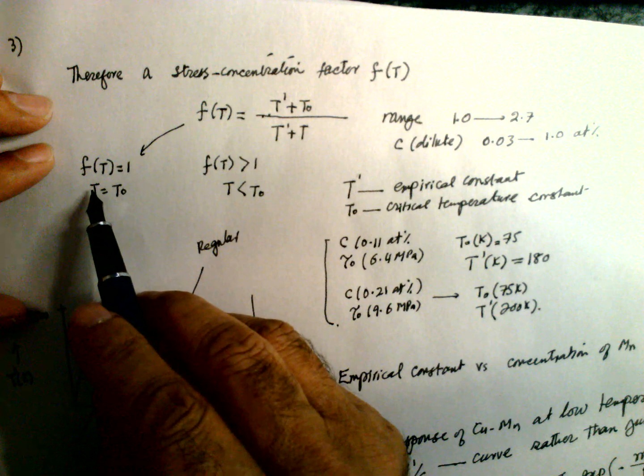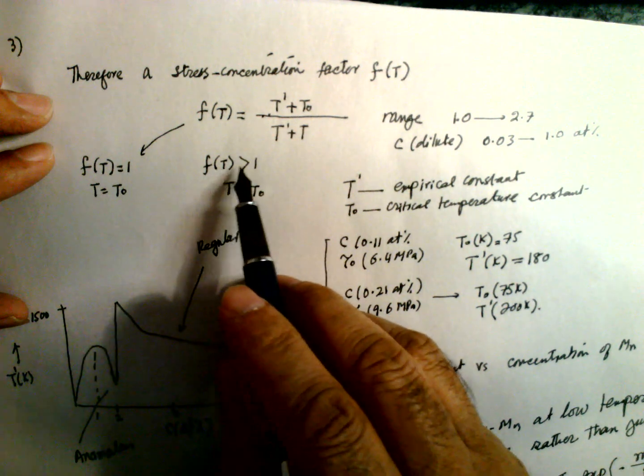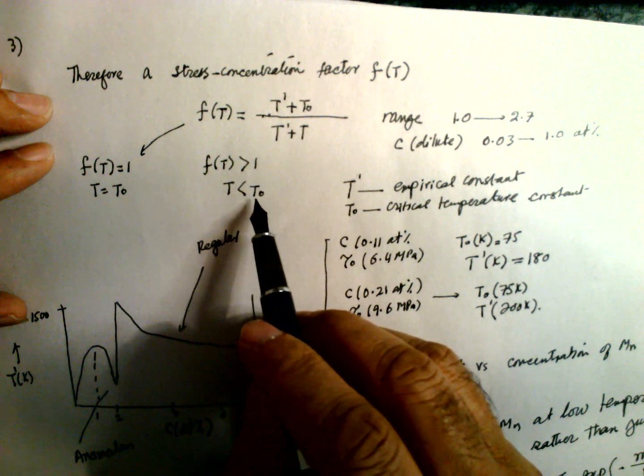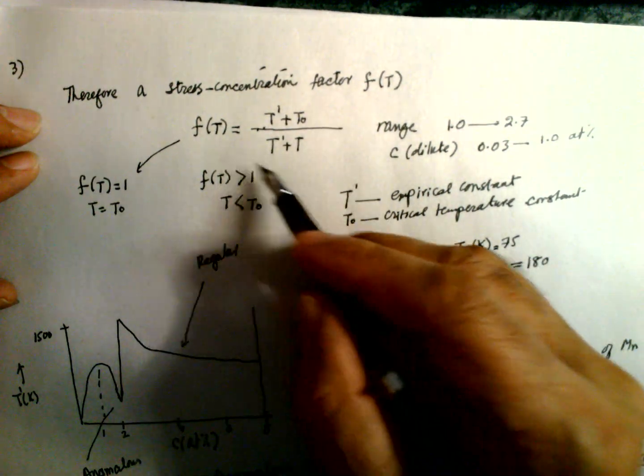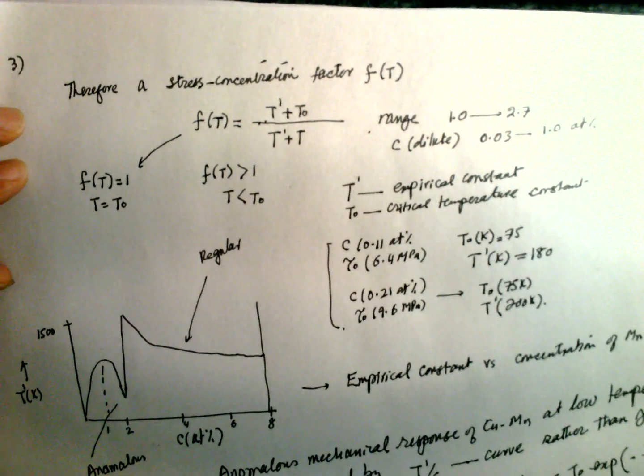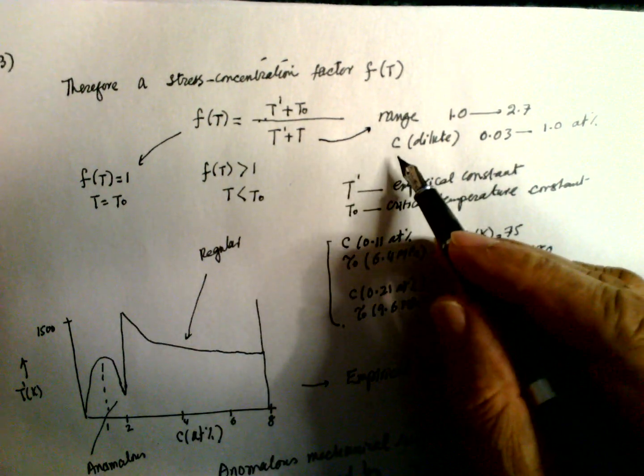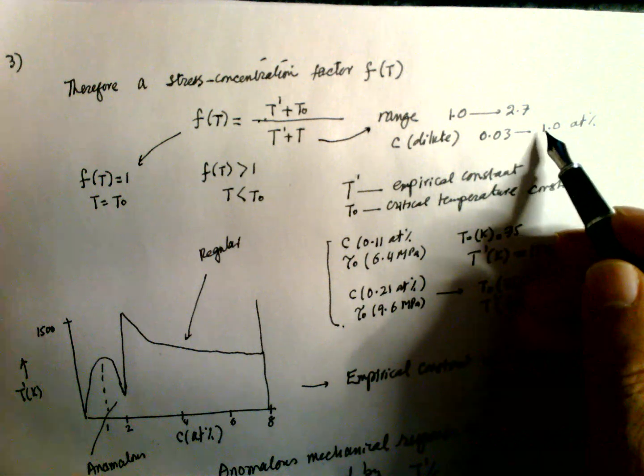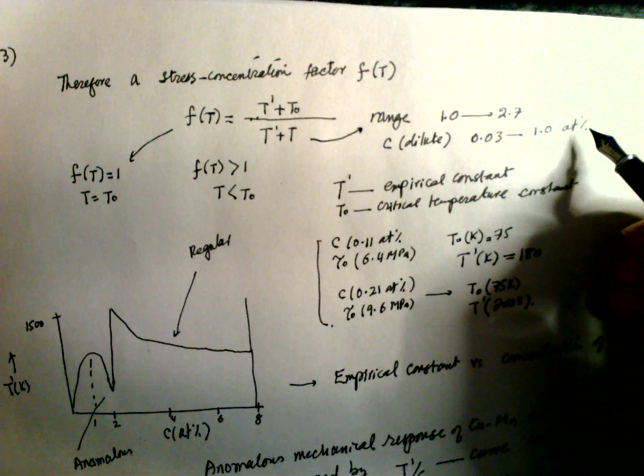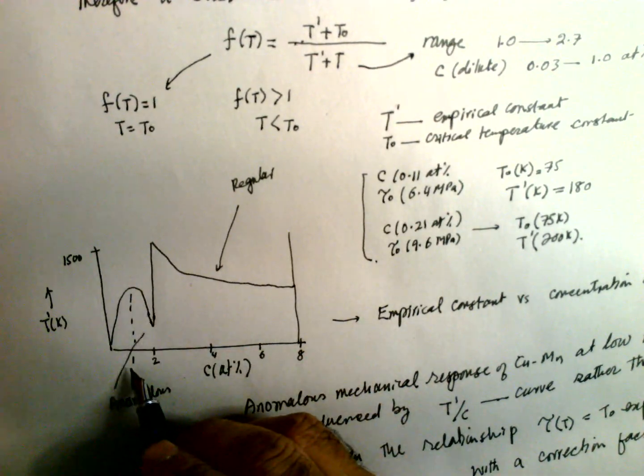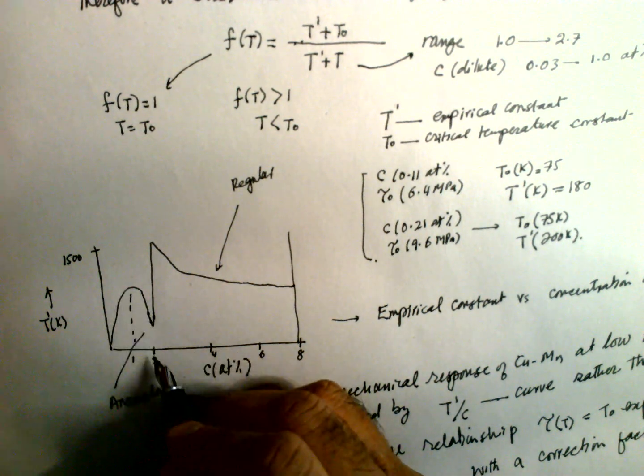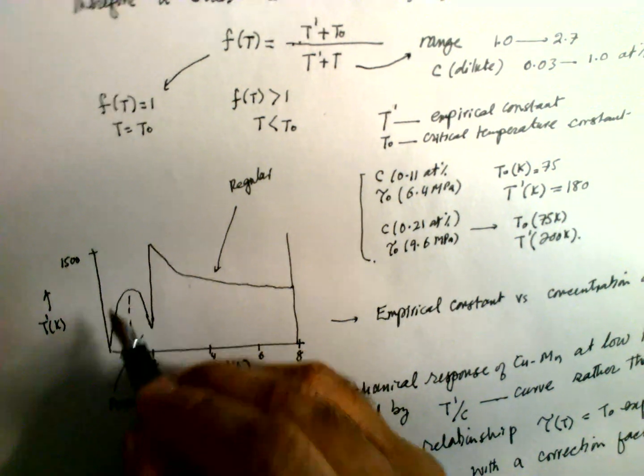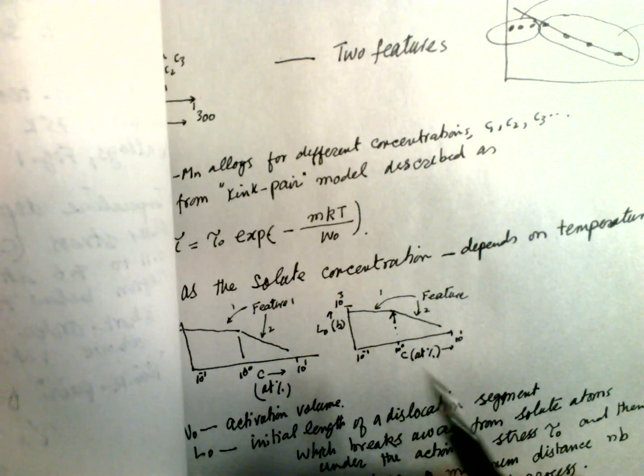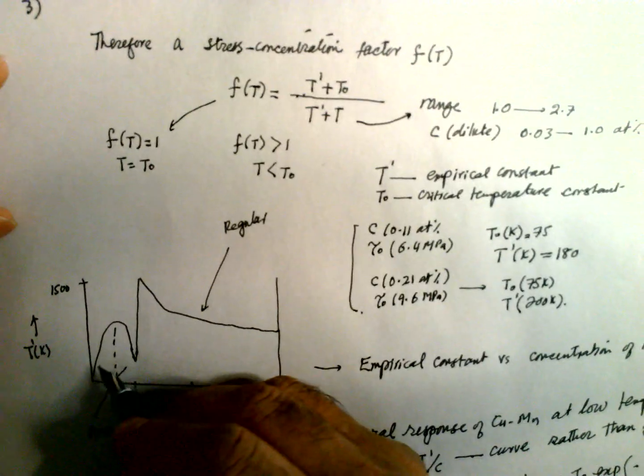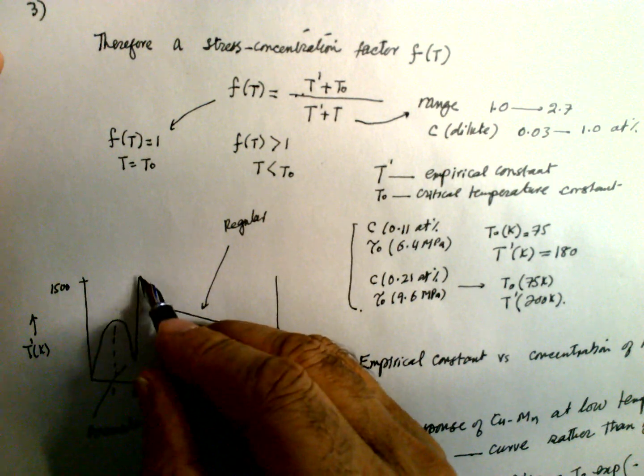So F(T) is equal to 1 where temperature is equal to T naught, and F(T) is greater than 1 when temperature is less than T naught. This function varies between 1 and 2.7 when the concentration is dilute, between 0.03 and 1 atomic percent. So this function changes as the concentration varies. It goes to a maximum, and this maximum is also the same as in the other graph. It has one profile, then it jumps again, and then it has this one.